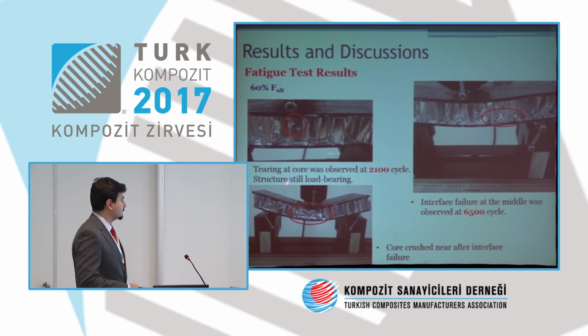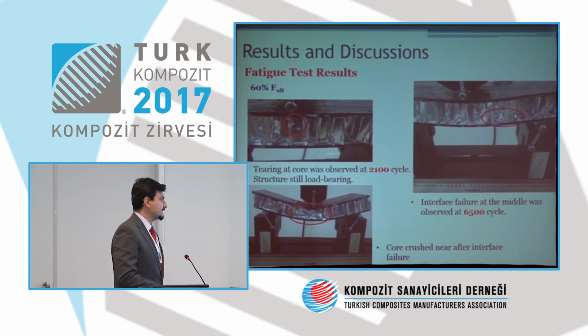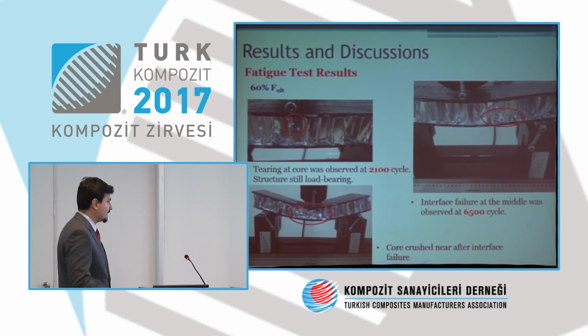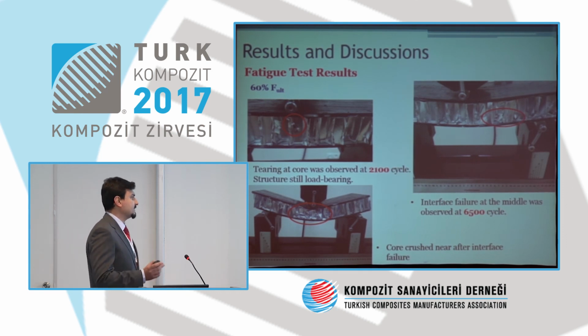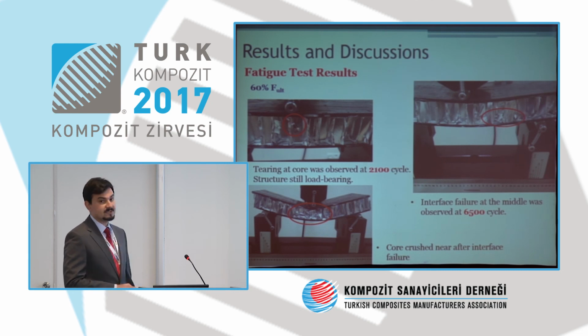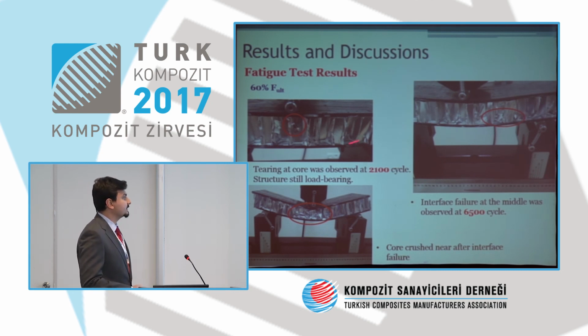Therefore, we didn't assume it as a first failure mode. The first failure mode for this stress level is interface failure, but it occurs in the middle of the specimen this time, at 6500 cycle. And then the last failure mode is the core crush still. We didn't wait for the face failure because it takes a lot of time. It's already failed specimens.